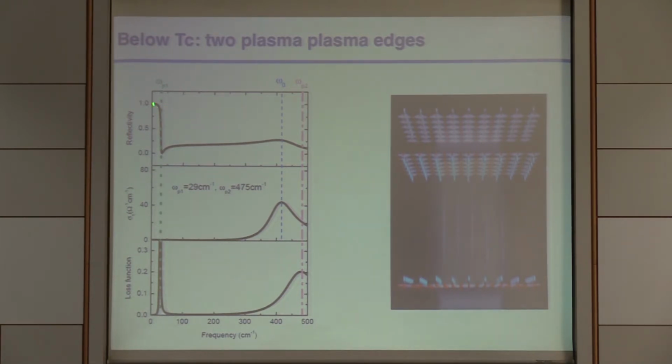And you can see this in reflectivity. There's this edge here, which is similar, which is this one. And then there's this thing, which is an edge, and the zero crossing of epsilon 1 is shown, where is it? Yeah, here, in the inverse of epsilon 1, that shows the existence of two modes and mixed modes, okay? And the position of these edges tells you how strong the tunneling is between this and between that.